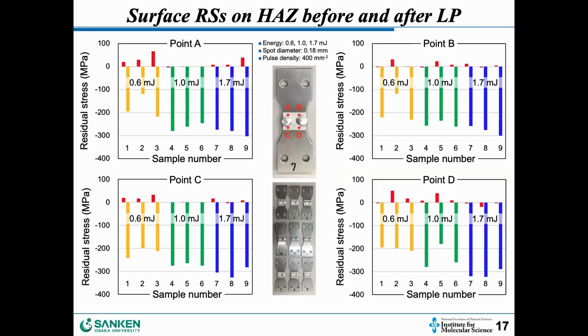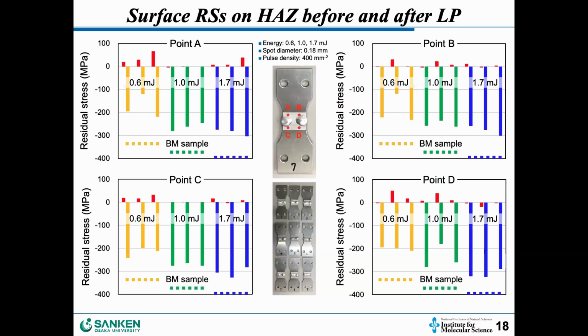So this one is the surface residual stress on the welds before and after laser peening for the 9 samples here. 1 to 9 mean the sample number, 1 to 3 or something. And we measure the four points A, B, C, and D here. You can see 0.6 millijoule induced less compression and has a larger scatter compared to 1 millijoule or 1.7 millijoule. So we selected 1.0 millijoule for the further experiment. However, for the fatigue experiment, we did each sample. This one again is the comparison to the result for the base material sample.